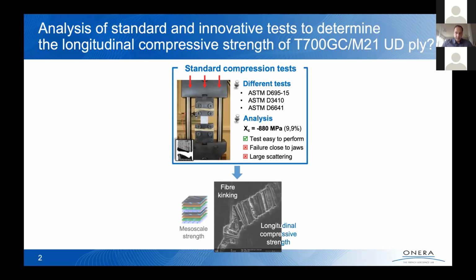So you can first perform a standard compression test. You can find here the reference of different standards that you can find in the literature. The major difference between such a test is the manner that you are going to transmit the compressive force into the specimen. You can introduce the loading through end loading. You can introduce the load through shear loading, or you can perform a combination of two. At ONERA, we have performed such a test on carbon epoxy composite materials, which is T700 M21. We have performed compressive tests introducing the compressive load through end loading.